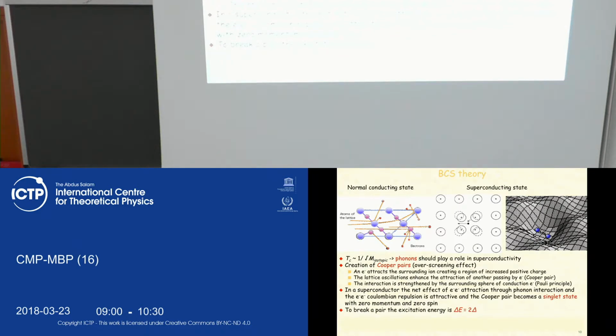Therefore, to speak about the bound state of just two electrons as a formation of a Cooper pair is not appropriate language, and it's much better to say that the Fermi-liquid ground state of the metal is unstable at sufficiently low temperatures with respect to formation of Cooper pairs. So the symmetry, namely U(1) symmetry, is broken, and therefore the phase transition to the superconducting state occurs.